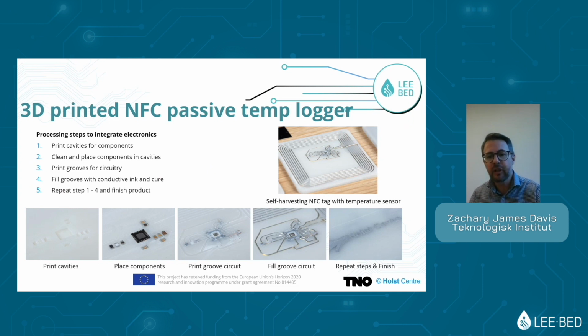Just to give you also a good example of what 3D printing is good at. This is a fully embedded temperature logging system where we print the whole substrate using 3D printing processes, then print the cavities, we then place the components in there, and then we print the grooves, and then we fill the grooves with the conductive material, and then we fully encapsulate it. So the whole thing is encapsulated in the polymer. This is a validation of the 3D printing capabilities of TNO and Holst Centre.